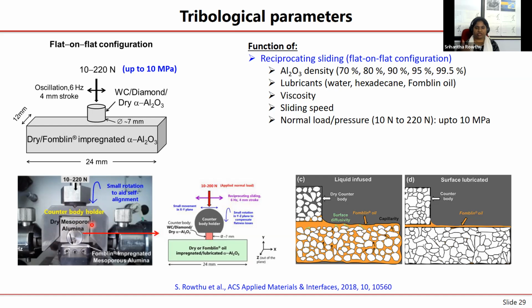This particular holder was specially designed because usually in the flat on flat configuration, when you try to bring them together, there can be, actually most of the time there will be, an alignment issue. If you do not correct it, it is possible that at one part there will be a huge pressure. That means locally a crack can initiate and the samples can fracture very badly. So you have to really make sure the surfaces are as flat, or as aligned, as possible with the other material. This particular holder is able to have a slight rotation in this manner, as well as move a little bit in this manner. This will help to better self-align the interfaces. So that is the sort of testing.